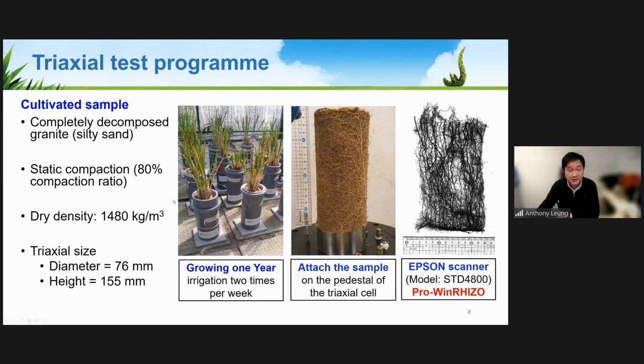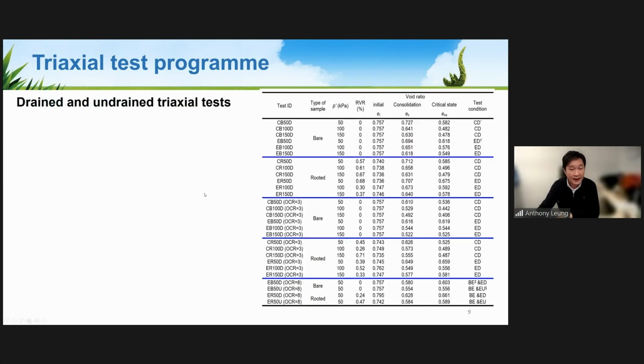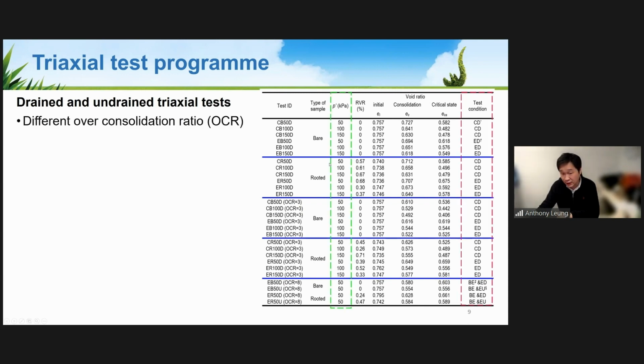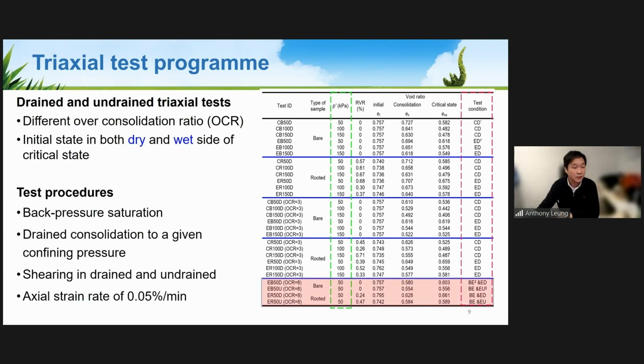So we perform a very standard triaxial test, actually, drained and undrained shearing under different confining pressures so that we can obtain the friction angle and cohesion. We also compact the sample to different initial densities. We follow a very classic, typical test procedure for triaxial testing. First, back pressure saturation, and then drained consolidation to a given confining pressure. And then we shear at a relatively slow rate to achieve a drained condition. And also we perform undrained shearing as well.